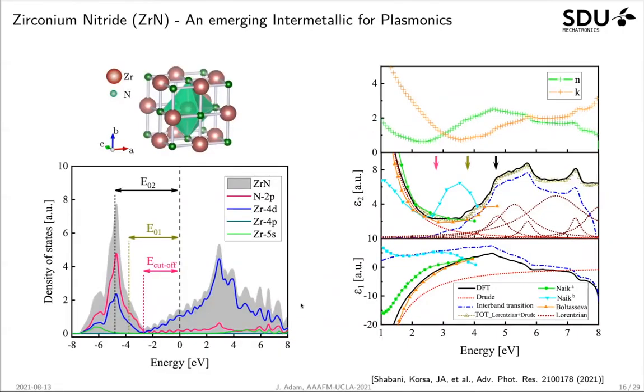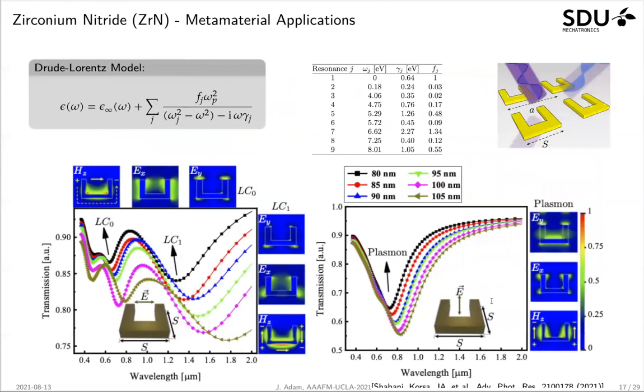Now for the intermetallic material zirconium nitride. We again started from atomistic simulations with the SIESTA package, extracted the density of states, and came up with n, k, epsilon_1, and epsilon_2 values, comparing these to recent experimental findings up to 4 eV and providing material data into the higher energy regime beyond that. We again looked at metamaterial applications with split-ring resonators, finding that by varying the geometry you can shift the plasmon resonance. Zirconium nitride is proposed as an excellent alternative for metamaterial applications.